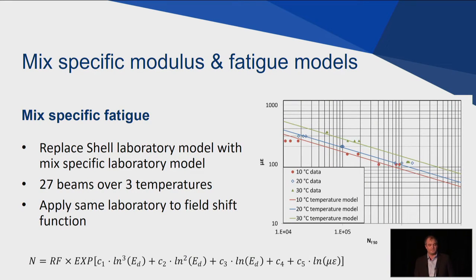So we test 27 beams divided over 3 temperatures, come up with a fatigue laboratory model for that particular material. The function is shown at the bottom there. So basically, the fatigue performance becomes a function of the strain level and the modulus of the material. And then you replace that Shell laboratory model, which again was developed for 12 mixes in Europe that have very little to do with current Australian mixes, with an actual model that was developed for your material.